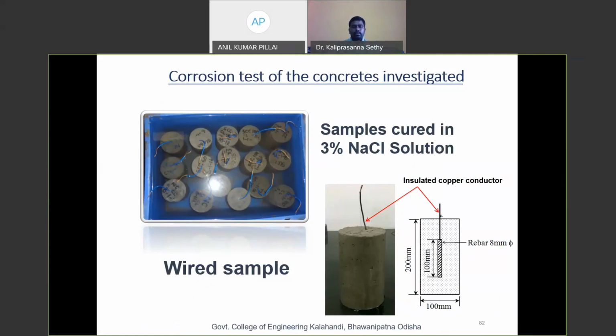And coming to the corrosion test of the concrete investigated. In this case, the sample preparation was a very challenging task for us, because we had to keep an 8 mm rebar inside, exactly at the middle of the sample. You can see from this schematic diagram, this 8 mm bar has to be connected with insulated copper wire, and this sample has to be placed inside the chloride solution.